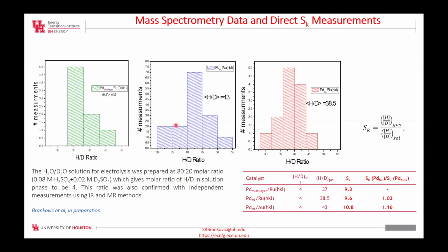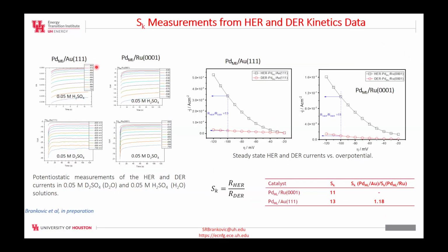If we do the same kind of measurements using mass spectroscopy, where we do electrolysis of a predetermined ratio of water and heavy water and measure the ratio of hydrogen to deuterium in the gas phase, we get similar separation factors. They're a little bit smaller, but the ratios that I talk about are fundamentally the same. And then we do similar measurements for the separation factors from the kinetic parameters, such as the current for pure deuterium sulfate dissolved in heavy water and regular water with sulfuric acid for different catalysts, and we see that the separation factors are again similar, and the ratio is about the same.